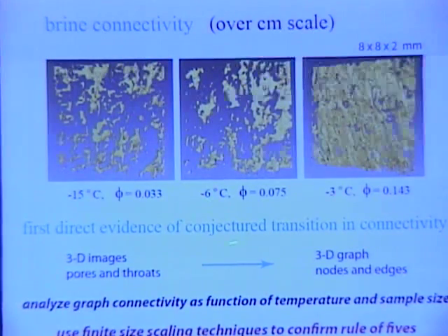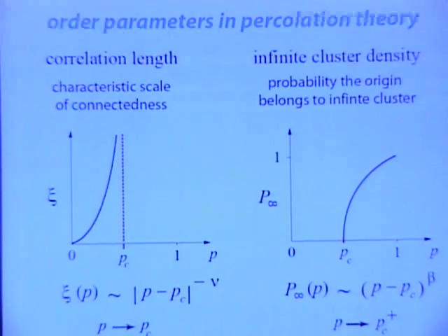So here's some of our X-ray tomography. We take 3D images of pores and throats, map that over to 3D graphs of nodes and edges, and then analyze the graph connectivity as a function of temperature and sample size, and use so-called finite size scaling techniques in physics to actually confirm my rule of fives. These are the order parameters in percolation theory. The correlation length, the characteristic scale of connectedness, diverges as you approach the critical point with a universal critical exponent. The so-called infinite cluster density: there's no infinite cluster below the threshold, and it takes off with a universal critical exponent. Universal means it doesn't depend on the details of the lattice. It only depends on the dimension that you're in. It captures the deep physics at the heart of a phase transition.